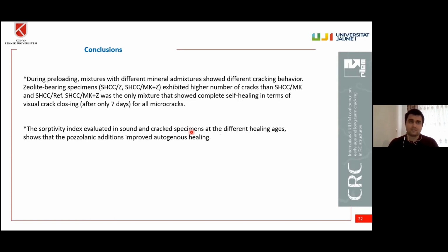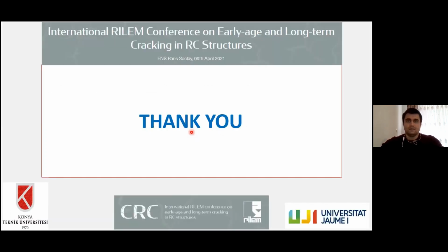During preloading, mixtures with different mineral admixtures showed different cracking behavior, as I also presented in the cracking results. Here, we can say that zeolite bearing specimens exhibited a higher number of cracks compared to other specimens, and this was also more favorable for the autogenous self-healing behavior. As we obtained the sorptivity index in both sound and cracked specimens at different healing ages, it shows that synergistic pozzolanic additions can improve autogenous healing. Thank you for listening to me.